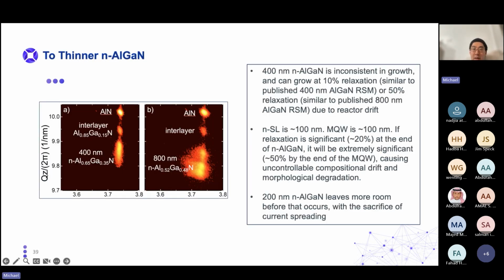And what we ended up figuring out was that because of the substrates being from a commercial supplier and there being variability in the substrates, this 400 nanometers of n-type AlGaN is actually not very consistent and can grow at small amounts of relaxation. So in the published work, we had around 10% relaxation here, and also slight spreading in composition. So main peak is around 65% aluminum, but it definitely does spread down a little bit in aluminum percentage. And what we figured out during this time was that some of the material would grow like this, and some of the RSMs would come out more like this. So even with the 400 nanometers thickness, with different substrates, the stress state would be different with our material.